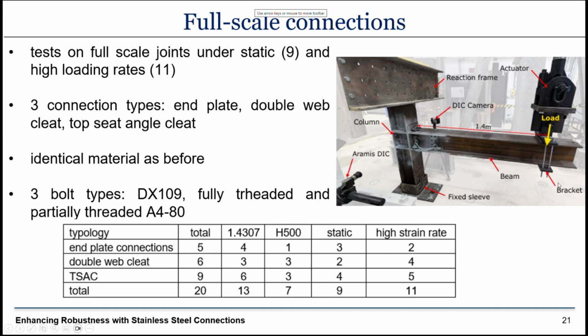We were able to apply loading speeds ranging from quasi-static conditions up to about 400 millimeters per second, so the actuator would move downwards at 400 millimeters per second. We had a look into three connection types: a traditional end plate connection, where we have an end plate welded on the beam and bolted on the column flange; a double web cleat connection, which is a conventional pinned connection, a nominally pinned connection; and we also had top and seat angle cleat connections, with angle cleats being bolted on the beam flange and the column flange.